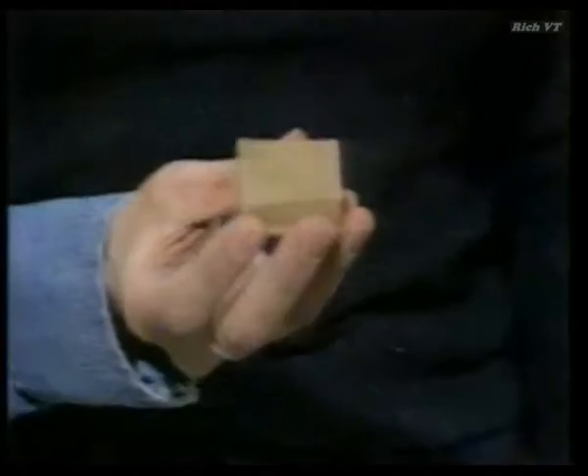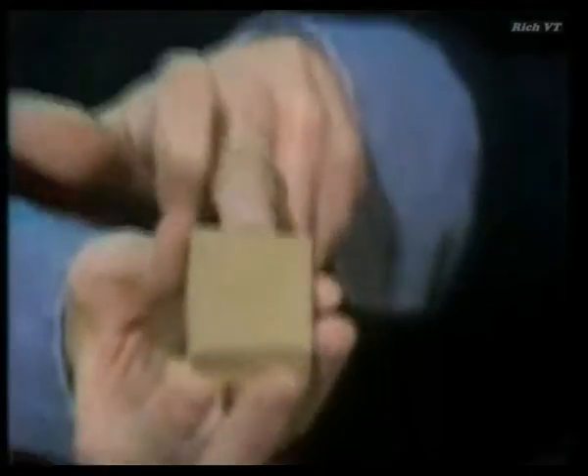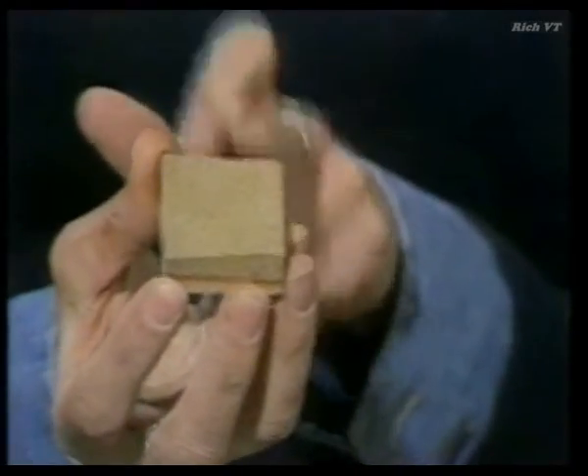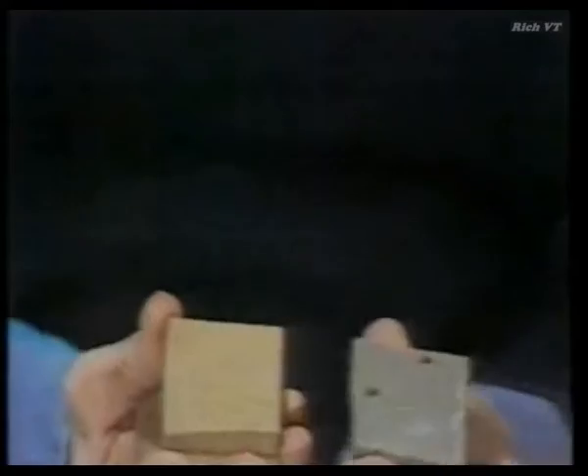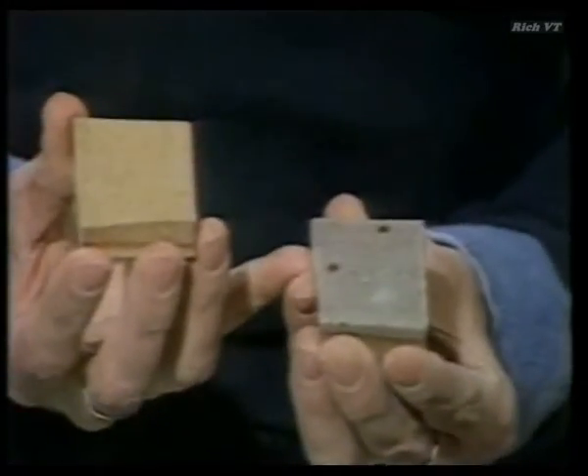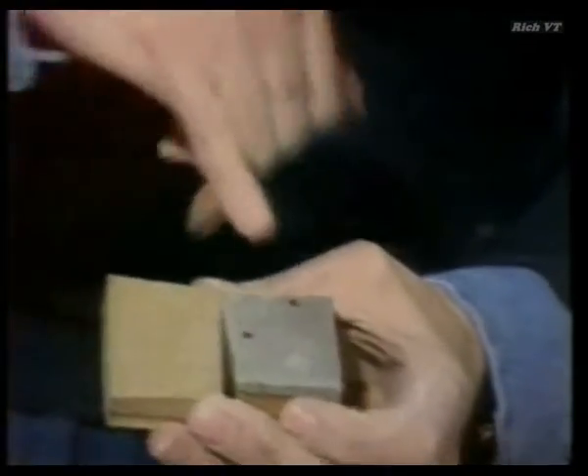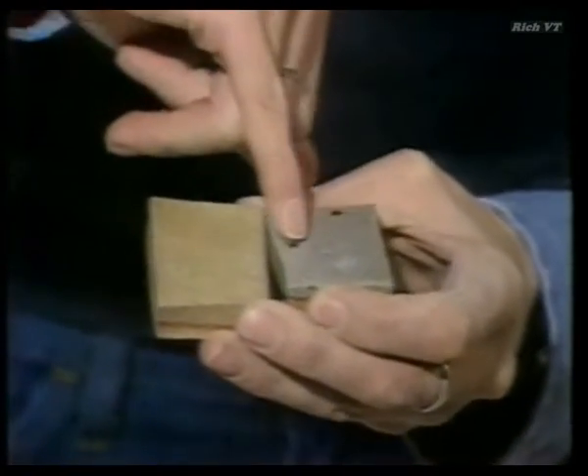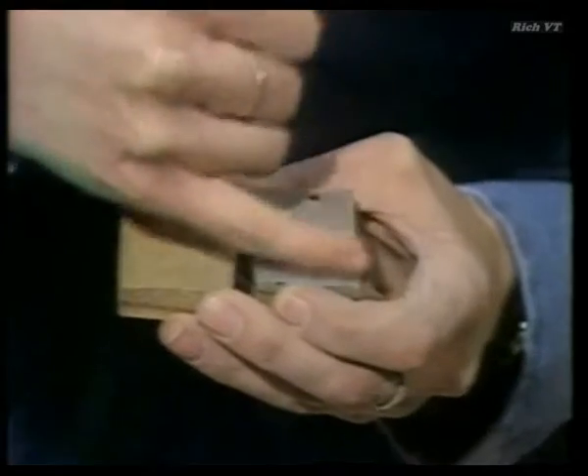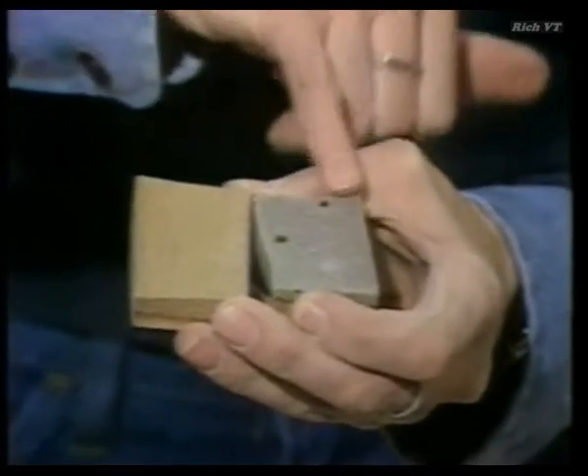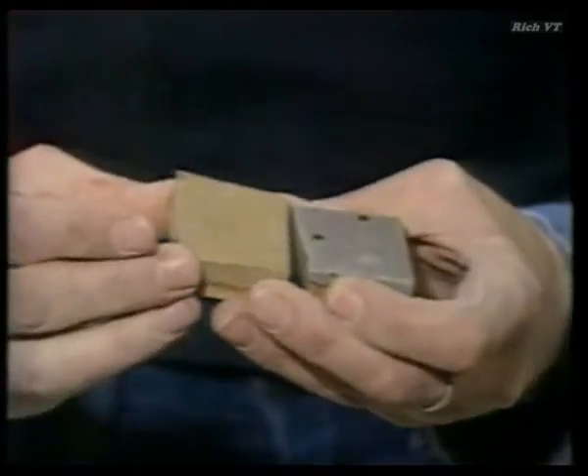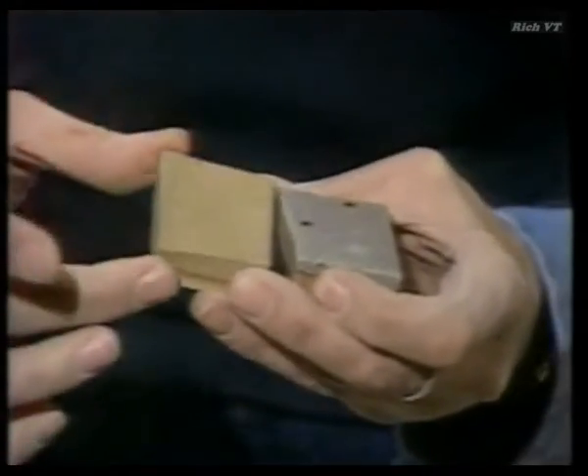We've seen how the kind of clay body you use affects the appearance of the glaze. This was our original glaze of 85 feldspar, 15 of whiting, and I've had it in this case in an oxidized firing in an electric kiln. Here's exactly the same glaze, but this time it has been fired in a reduction firing, in a gas kiln, and you can see that the glazes are very different. In the case of the reduced version, we have quite a lot of speckling on the glaze, a rather more interesting surface, and certainly a darker colour. The oxidized version, on the other hand, is very much cleaner looking and paler in colour.